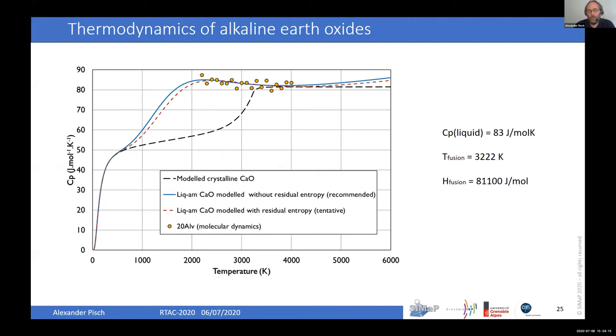However, what we did, we can calculate the heat capacity as a function of temperature. This is done by classical molecular dynamics, but we checked the values also by ab initio for some points. And you see, we confirm the higher CP of the liquid, which is around 80 to 83 joules per mole per Kelvin, which is the one also favored in the Gurvich compilation. So here, clearly, the estimation by Janaf is wrong, and it should be corrected.